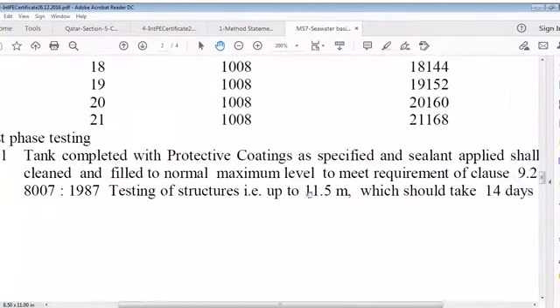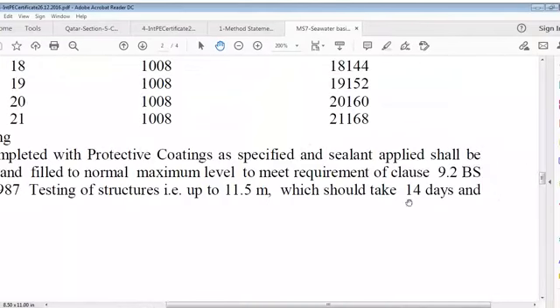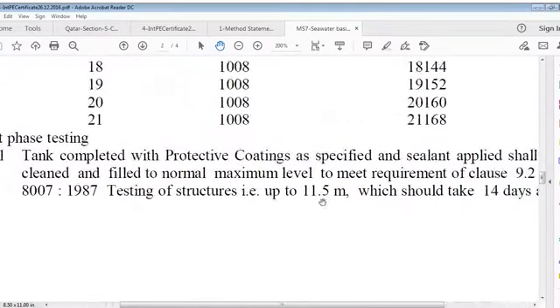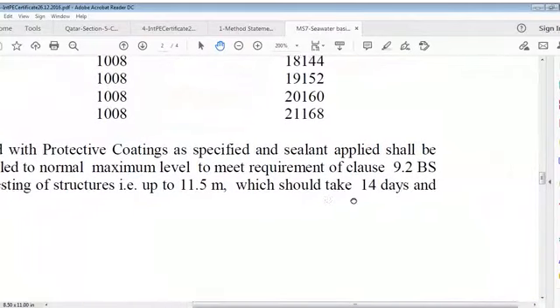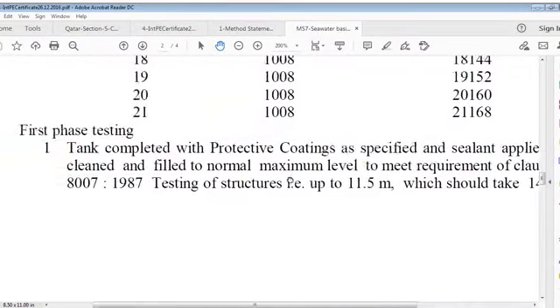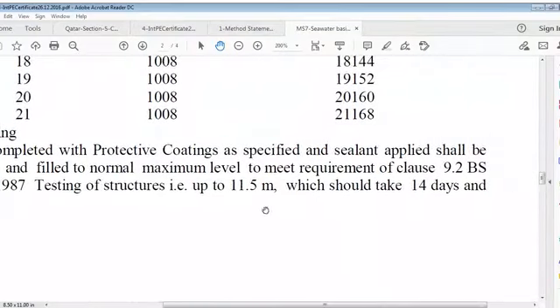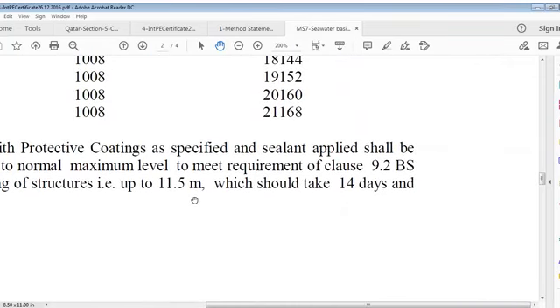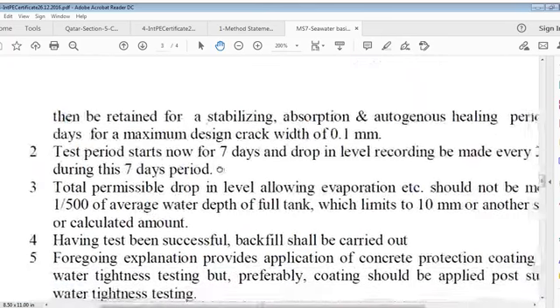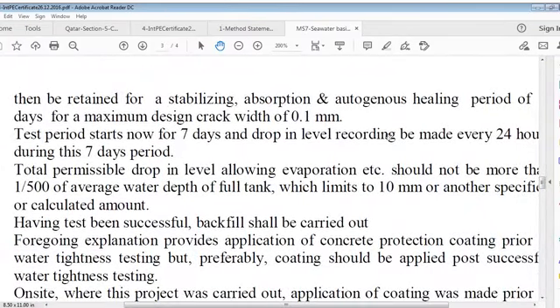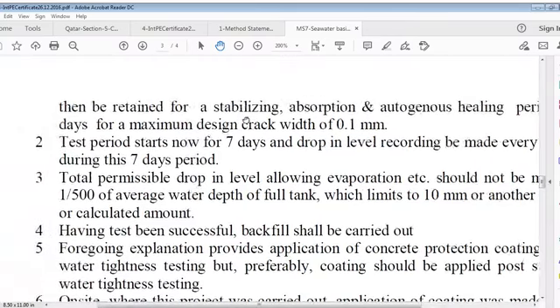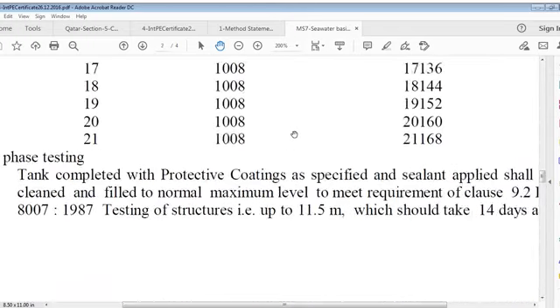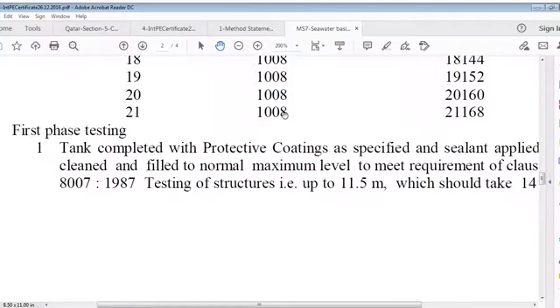First phase testing. Tank completed with protective coatings as specified and sealant applied shall be cleaned and filled to normal maximum level to meet requirement of clause 9.2 of BS 8007:1987. Testing of structure, that is up to 11.5 meter, should take 14 days, and then we retain for a stabilizing, absorption and autogenous healing period of 7 days for maximum design crack width of 0.1 mm. What it says? It says first phase testing. Tank completed with protective coating as specified and sealed.